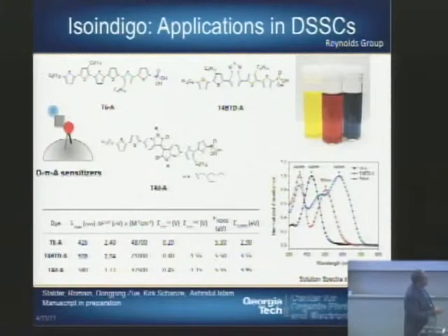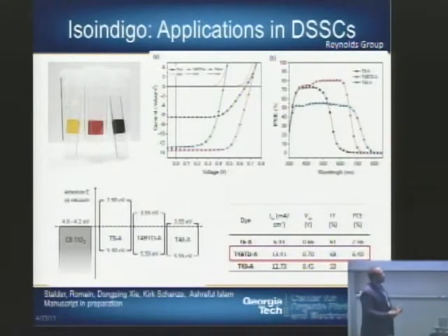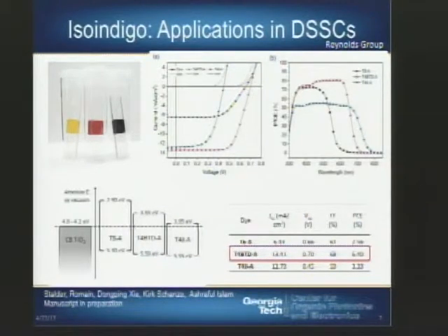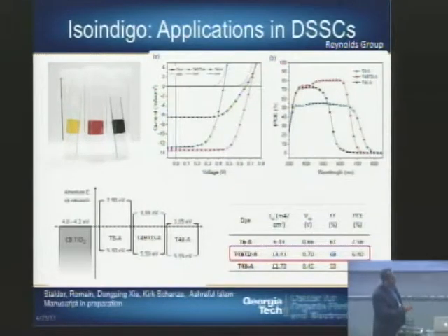And then you have a mid-band gap polymer, the benzothiodiazole. And then you have a large band gap polymer, which is the thiophene base. So we can look at these to see how they behave in terms of the efficiency of the solar cell. This particular slide shows that outcome with these molecules placed on TiO2. If you look at the large bandgap molecule here, we have a power conversion efficiency of about 2.5. When we look at the mid bandgap polymer, we're up to about 6.4%. And with the isoindigo, we're at about 3.4%.